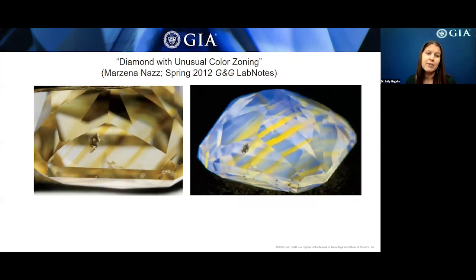Next up, I'm going to talk about this half-carat fancy intense orange yellow diamond. It had rather unusual color zoning. This diamond was colored by a broad absorption band centered at 480 nanometers. This is sometimes observed in natural yellow to orange diamonds. However, we don't yet know the composition or the formation of this 480 nanometer band.